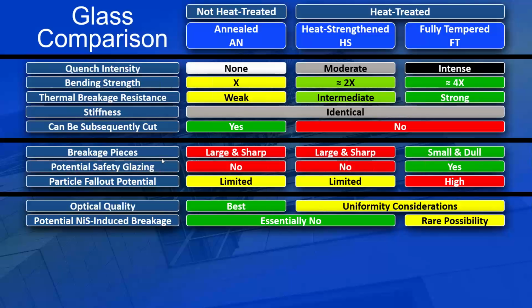Back to this chart again, if we just recap: fully tempered glass is approximately 4 times the strength of annealed glass. Heat strengthened glass is a good middle ground if tempered glass is not required, but the IGUs are large enough that we want to resist more thermal stress. And we are also looking for glass retainage should that glass ever break, and we want to retain those lights in the IGU.